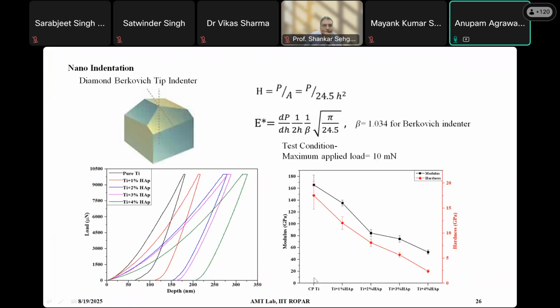For pure titanium it is very high, and for titanium mixed with 4% hydroxyapatite, it is as low as about 50 GPa. And if you remember, the cortical bone was about 20 GPa. So we are coming closer to the modulus of the bone. However, at 4% we face some issues, and 2 and 3% were quite ideal, where the strength is about one third of what commercially pure titanium has.